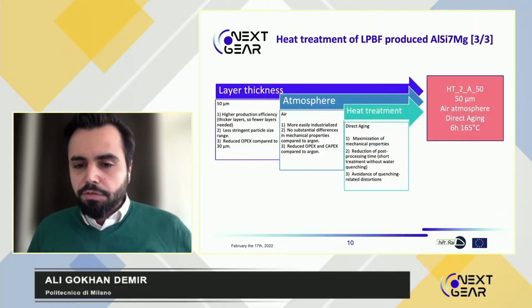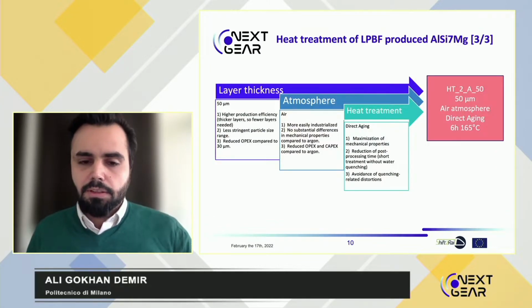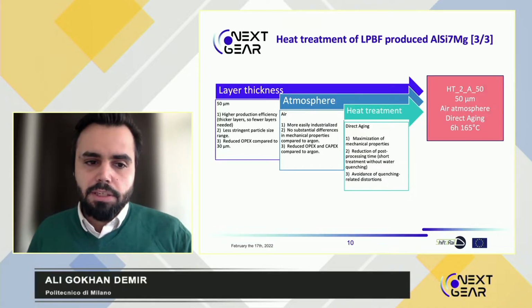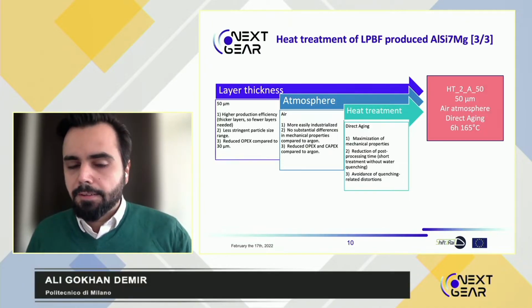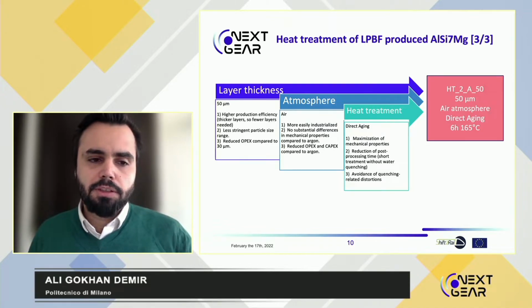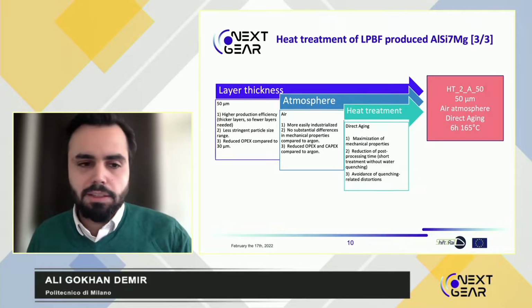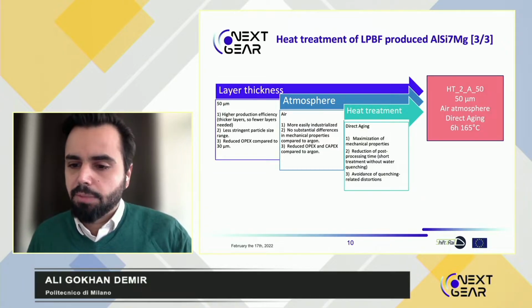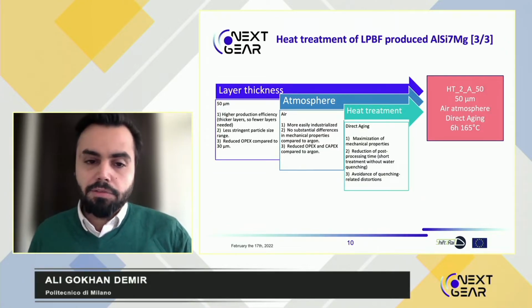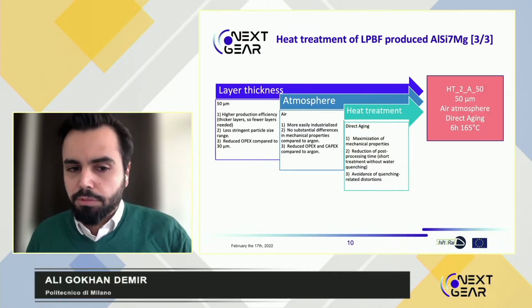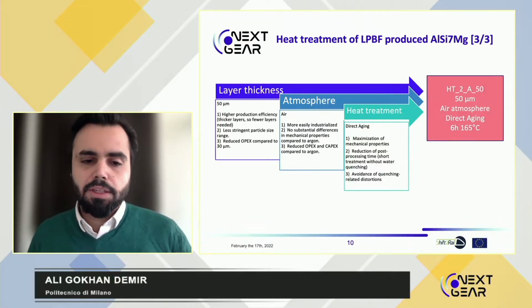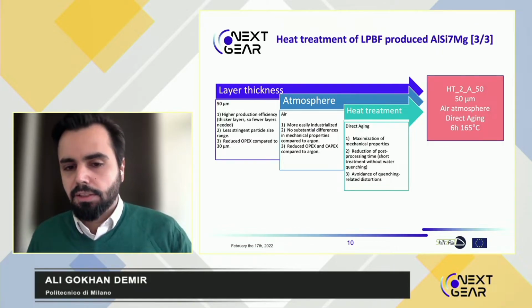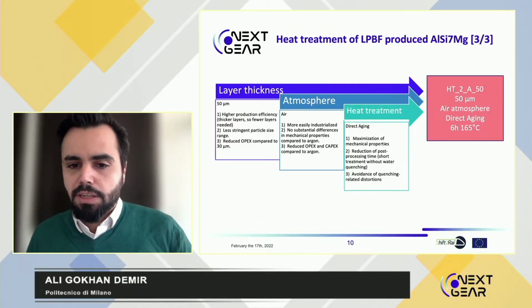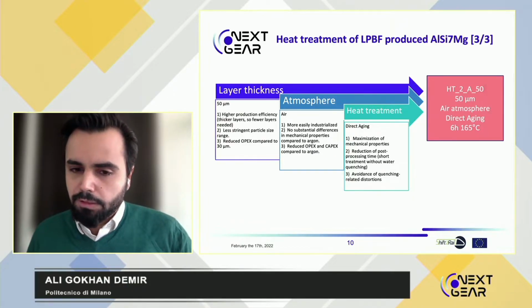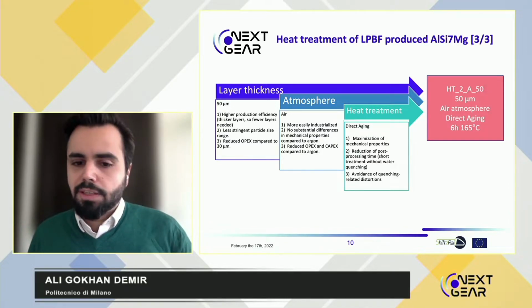Very quickly, going into the final recipe of manufacturing of this alloy for railways applications, we said that we will go for a quicker manufacturing in laser powder bed fusion by increasing the layer thickness, because we found out that the mechanical properties were still adequate after a heat treatment in air atmosphere. And the heat treatment was a direct aging heat treatment, where my colleagues showed that the mechanical properties were very good. The post-processing time was reduced.